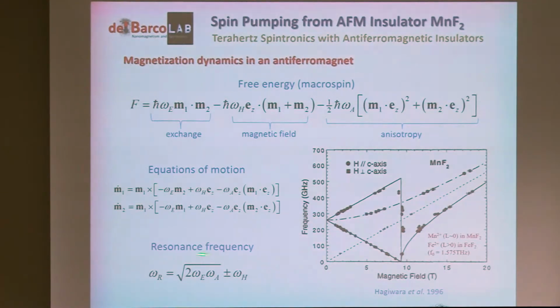You solve the equations of motion, and you'll find that there is a resonance frequency. So you irradiate your system with a particular frequency set up by the product of the exchange energy and the anisotropy energy. You will drive the system into a coherent precession. That is the exchange amplification that you don't get in ferromagnets. In ferromagnets, that frequency is just set up by the anisotropy. And this can be actually very high. In manganese difluoride, it is 262 or 261 gigahertz, I believe, at zero field.